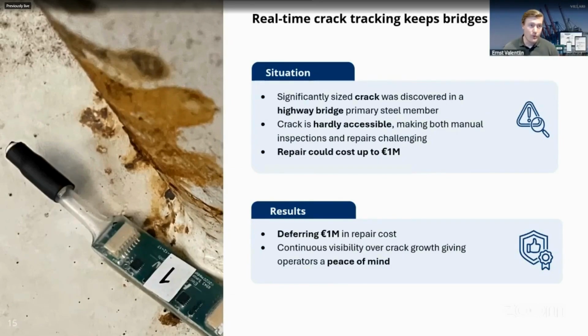Calculations were done on what the cost would be and what the impact would be to have these locations repaired, and they turned out to be massive, mainly because due to the specific location and the hard accessibility, the entire highway would have been closed for several days to be able to perform this repair. Therefore, of course, there's a high motivation to try to defer that repair cost and keep the situation in control by different means. In this case, that would mean a very frequent inspection of a very difficult to access location, which would also be a very costly endeavor.